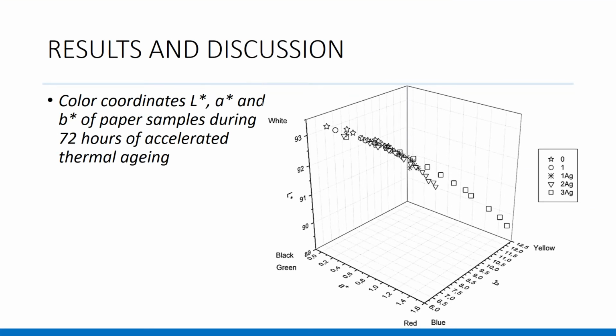From the color coordinates measurements presented in this slide, it is clearly visible that the cellulose and base paper are most stable and there is no drastic change of the color. For the other 3 examined paper samples treated with 1, 2 and 3 milliliter silver water, the color change occurs after 36 hours of aging. The values of the color parameter decrease, which means that the paper is getting darker and yellowish. The change is significant and with a large step for the paper sample treated with 3 milliliters of silver water.